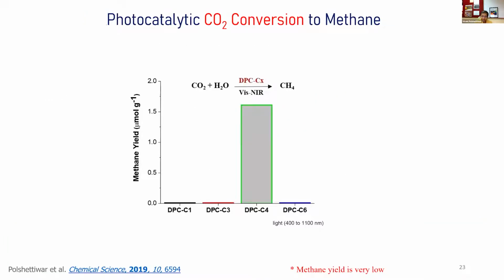We also explored this catalyst for CO2 reduction, which was the main project, and we reacted CO2 with water using the black gold and the xenon lamp visible near IR light, and we were able to convert CO2 to methane, with a yield of 1.5 micromole per gram, which is 10 times better than a simple gold nanoparticle. So clearly indicating the impact of plasmonics, the hotspots, in increasing the catalytic activity.